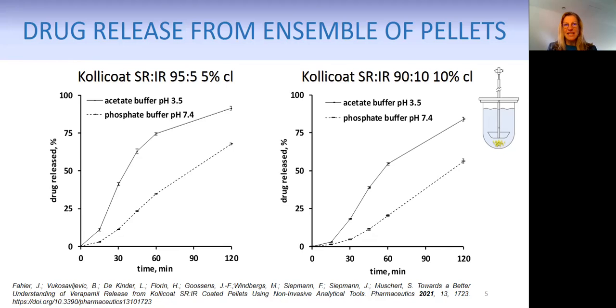However, in acetate buffer, in slightly acidic medium, we always had faster drug release. Nevertheless, the coating blend and the coating thickness. In phosphate buffer, you can see drug release is slower. And generally, we have slower drug release with the 90-10 blends with a thicker film coating. So although we have a higher amount of the soluble compound in the film coating, we still have slower drug release. So meaning the coating thickness in this special case was more important than the amount of Kollicoat IR within the film coating.